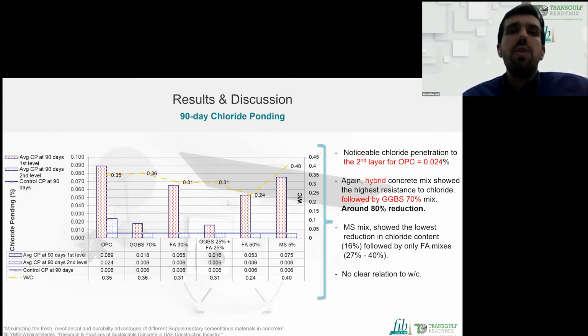And similarly, we evaluated here the 90-day chloride ponding. There was no clear relation here with the water cement ratio for this part of the study. However, noticeable chloride penetration on the second layer in the OPC was the highest. You can see it's 0.024 as a concentration, while the rest were very low, remarkably low to be measured. However, it was identified as 0.006.